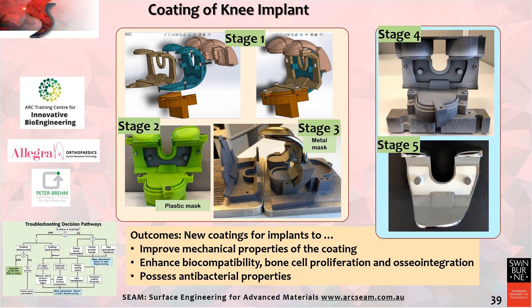The coating must be applied to an orthopedic device. There are five stages: one, the implant is measured and data input into a graphics program; two, make a plastic mock-up of a clamshell mask so the coating is deposited only onto specified surfaces; three, make up a metal clamshell mask by conventional additive manufacturing; four, mask the implant; five, spray the bioceramic coating onto the implant. Therefore, the desirable microstructure has been precisely located on the orthopedic appliance to manufacture the functional coating. This is an achievement at TRL 6.